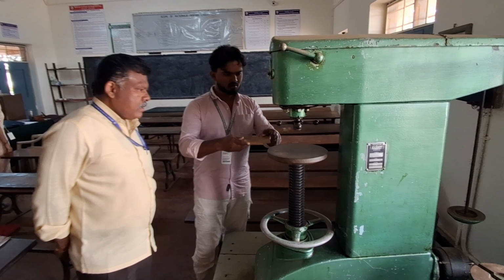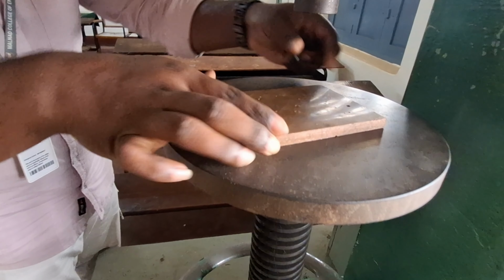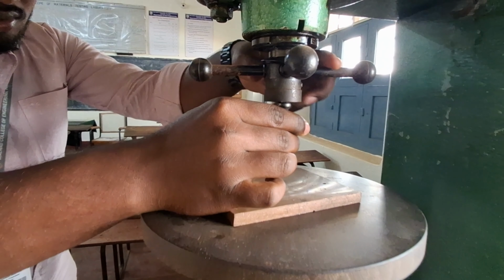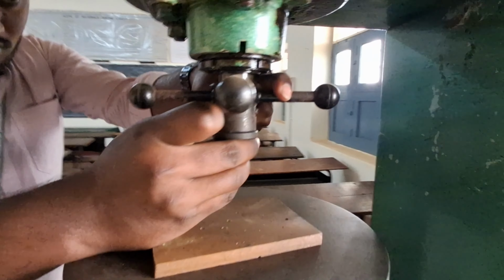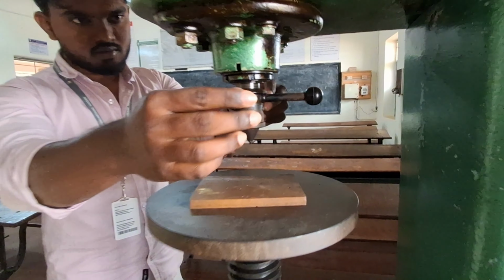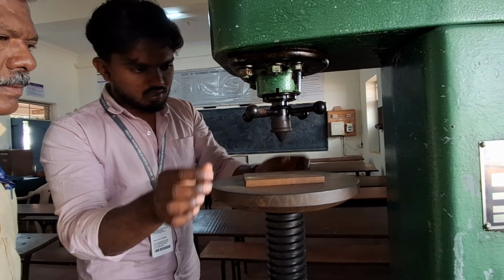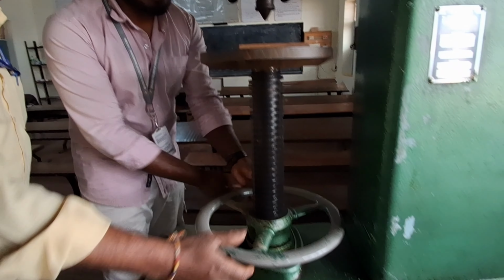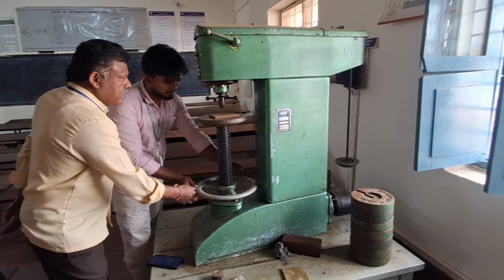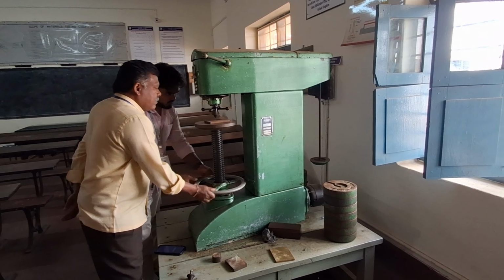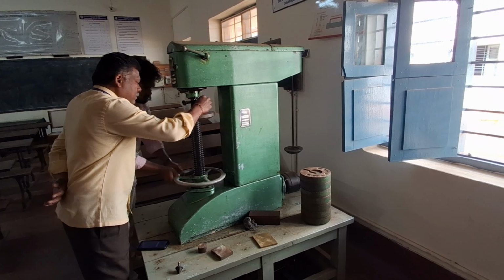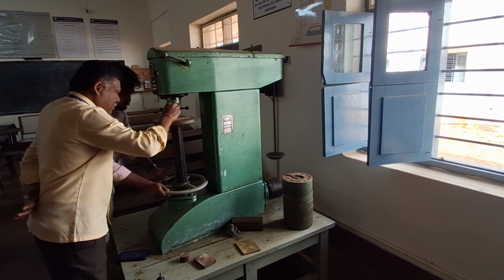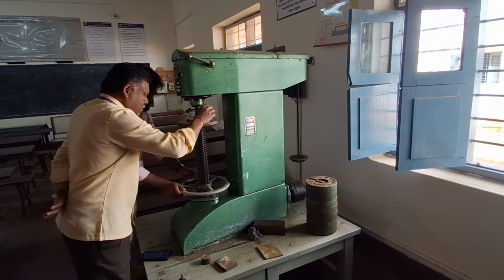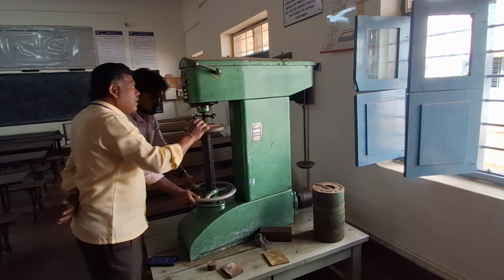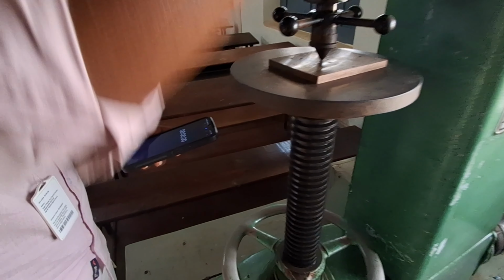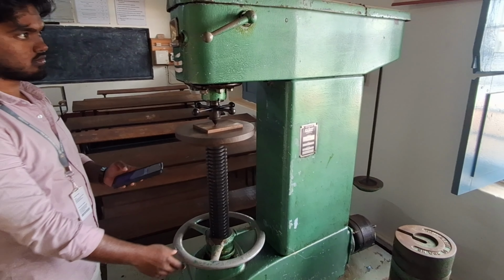Now, let us conduct the experiment for non-ferrous materials. Here, the non-ferrous test specimen is placed properly on the anvil of the Brinell's hardness testing machine. Using the hand wheel, the anvil is raised slowly until the specimen just comes in contact with the steel ball. For non-ferrous materials, a 5 mm steel ball is used. Now, a load of about 250 kilograms is applied. As the hand wheel is turned further, the load is applied gradually on the specimen. The load is applied smoothly to ensure a proper impression is formed.